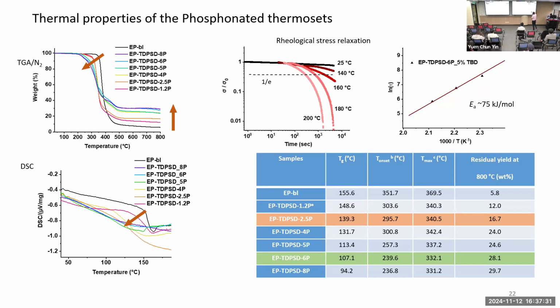And what we also calculate is activation energy. How much energy is needed to recreate this bond. And it is in a very good region of 75 kilojoule per mole. And what is also important is you need to know there is a certain amount of phosphorus you need to get this recyclability, I would say.